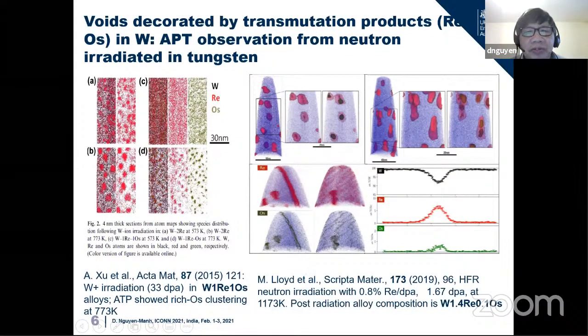What I'm showing here is atom probe tomography experimental observation of a recent discovery of a phenomenon called void decorated by transmutation. Here is an atom probe tomography figure showing that inside the precipitate you have rhenium, shown in red, and osmium, shown in green, forming under neutron irradiation. It is in single crystalline tungsten, but also in polycrystalline tungsten, shown here at the grain boundary. You see the accumulation of rhenium and osmium at the grain boundary.